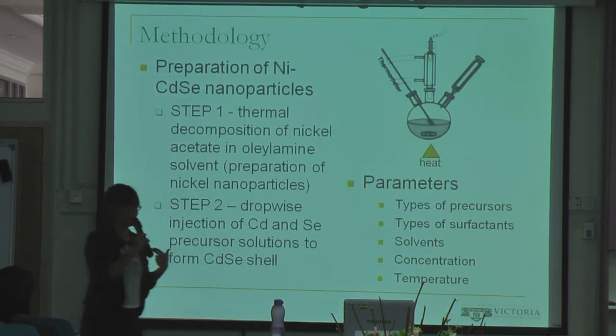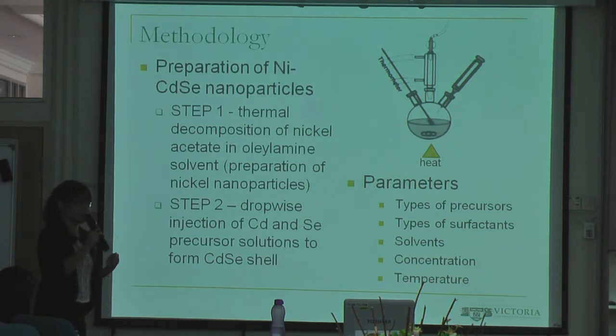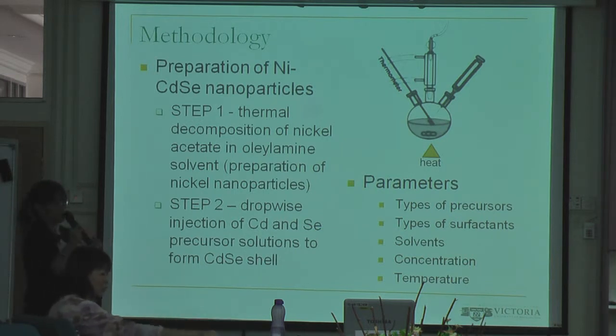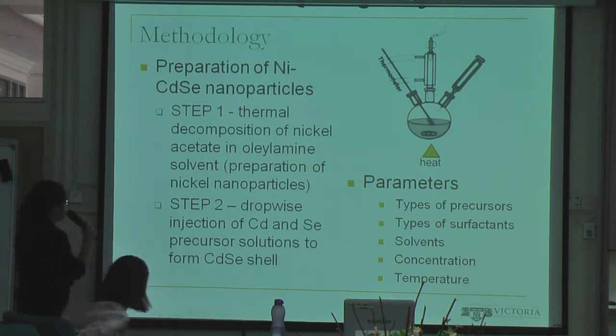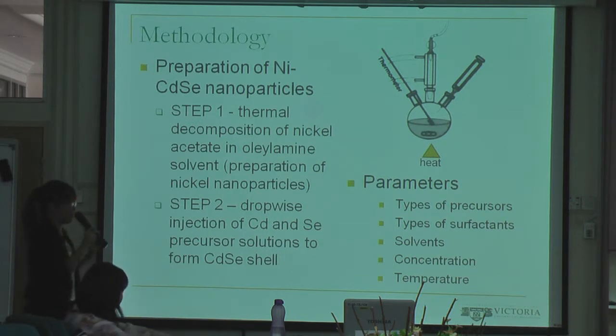Now I will go into the methodology, and the first part involves the preparation of these bifunctional nanostructures. Essentially, it's a two-step process. The preparation is usually carried out in a 3-neck flask under nitrogen atmosphere. The first step is the preparation of the magnetic component, which is nickel nanoparticles, prepared by the thermal decomposition of nickel acetate in oleylamine. The second step is to form the fluorescent cadmium selenide shell on the surface of the nickel seeds, achieved by the injection of cadmium and selenium precursors into the reaction mixture. In my research, I studied a number of parameters, including types of precursors, types of surfactants, solvents, concentration, and temperature.